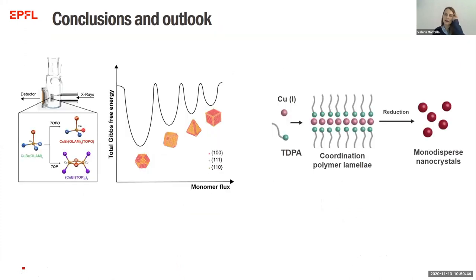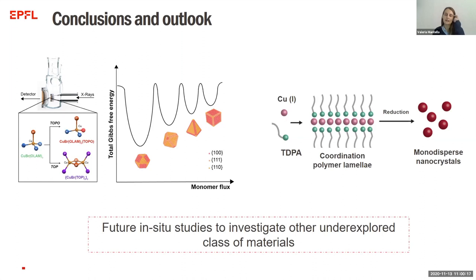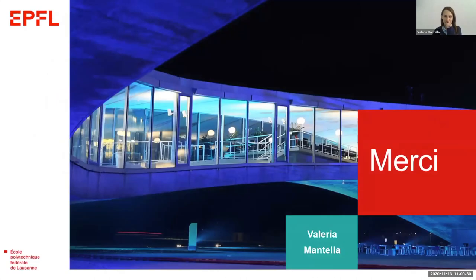And so in conclusion, in our in situ works, we have revealed that ligands are not simply acting as surface passivating agents, but they too take part in the reactions by forming, in one case, metallic complexes that have an impact on the monomer release, and in the other case, by forming these lamella hotspots, which are responsible for the monodispersity of the final nanoparticles. And so, as a future perspective, these findings motivate us to perform similar in situ studies, also to investigate other underexplored classes of materials. And with this, I would like to thank you for your attention.